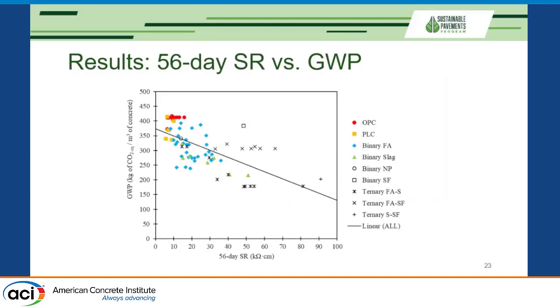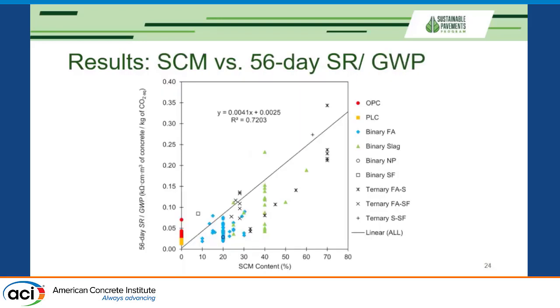The next one is also the relation between surface resistivity, which is our proxy for durability, and global warming potential. Keep in mind, not for all mixes we had a 56-day test. We have a lot more data for the 28-day test, which you can find in the paper, but generally speaking, mixes with higher surface resistivity generally have lower values of GWP, whereas mixes with very low surface resistivity generally have very high GWP. This is a very important trend, and it shows us that often we can achieve durability and environmental sustainability in synergy. These two goals are not at odds.